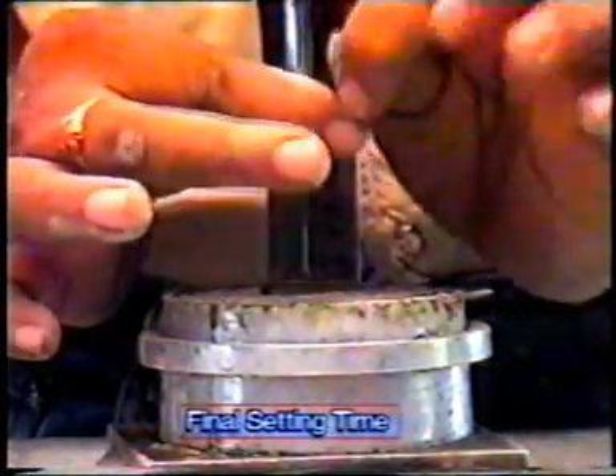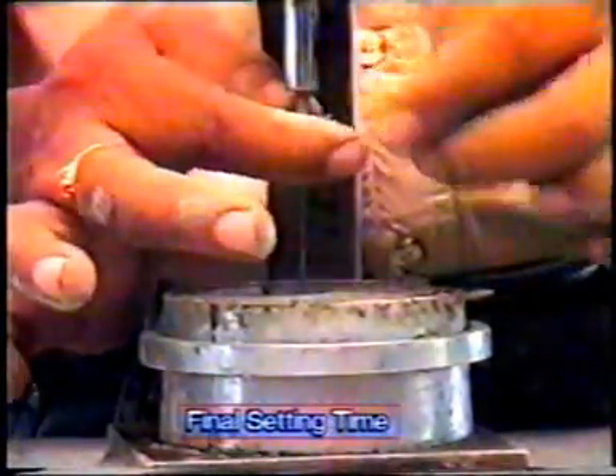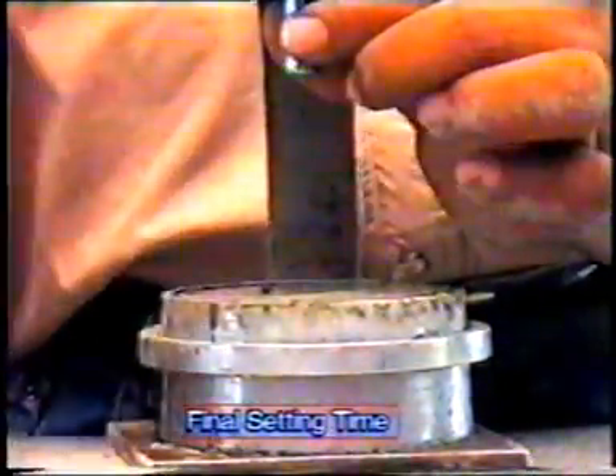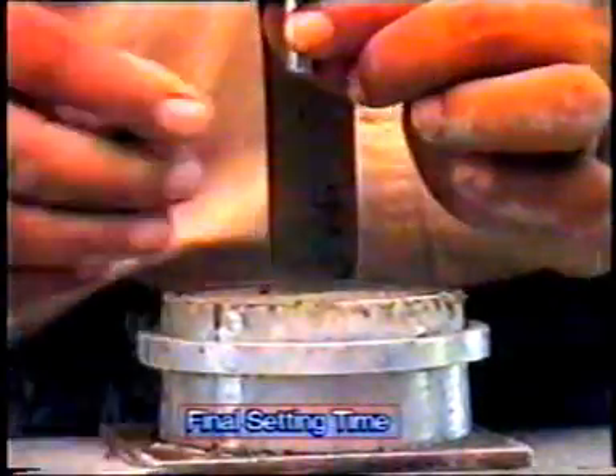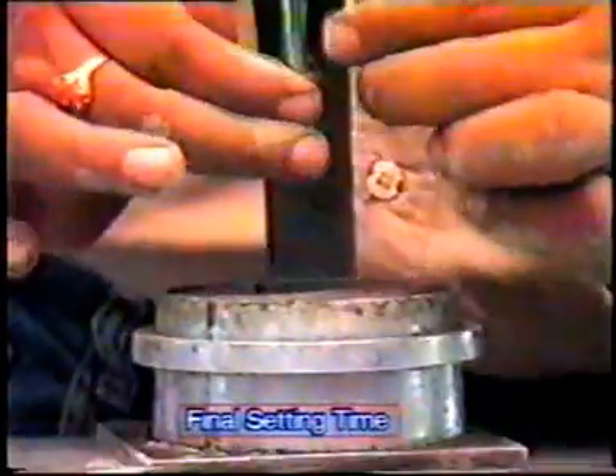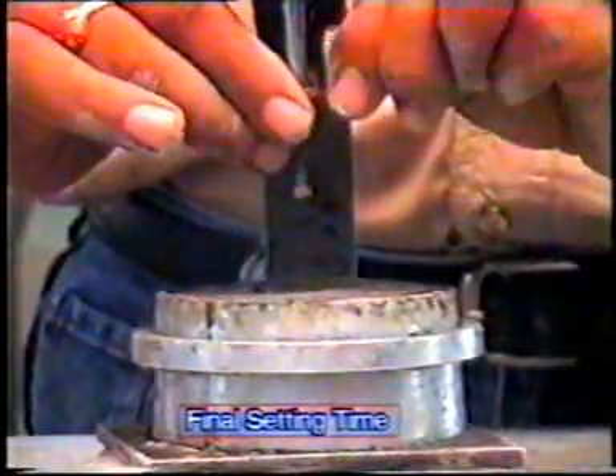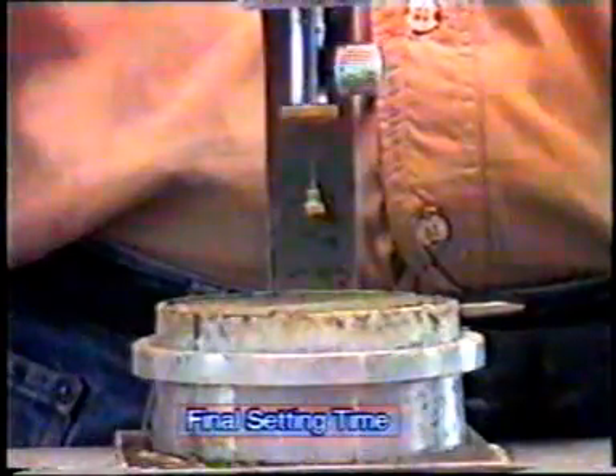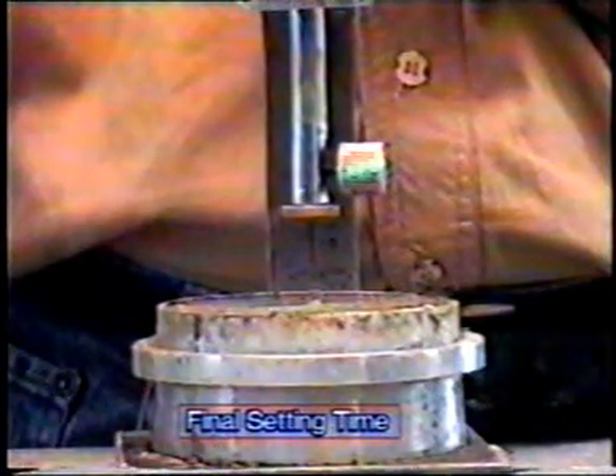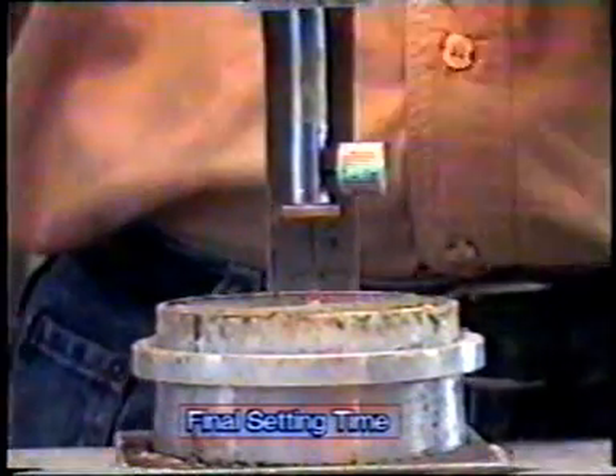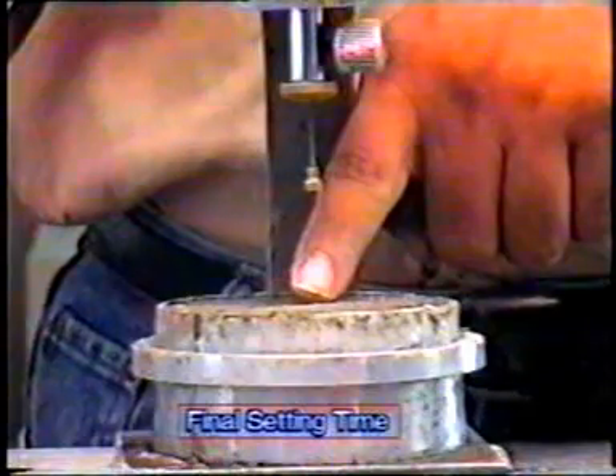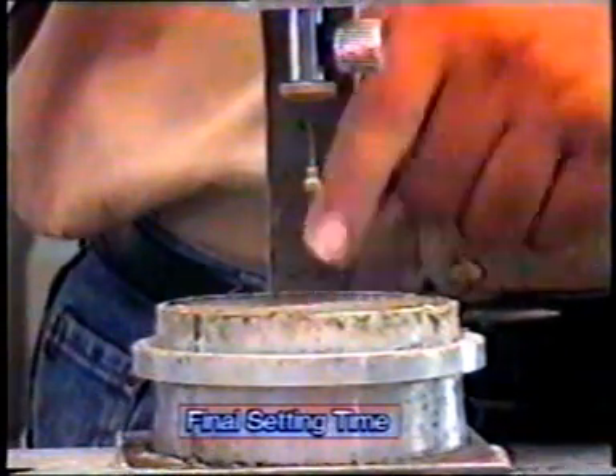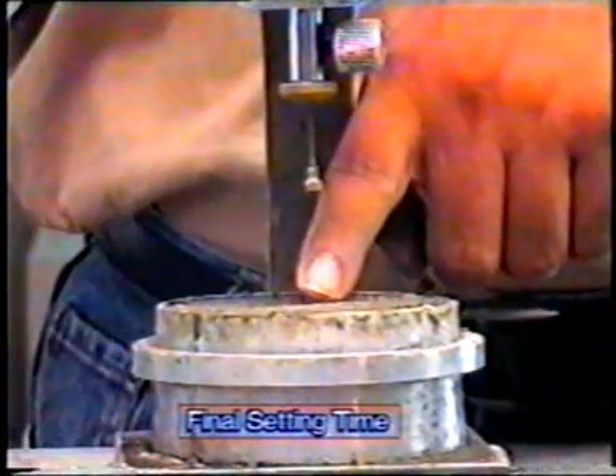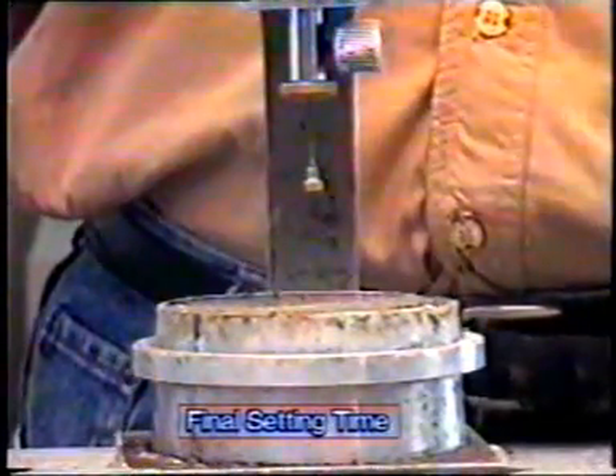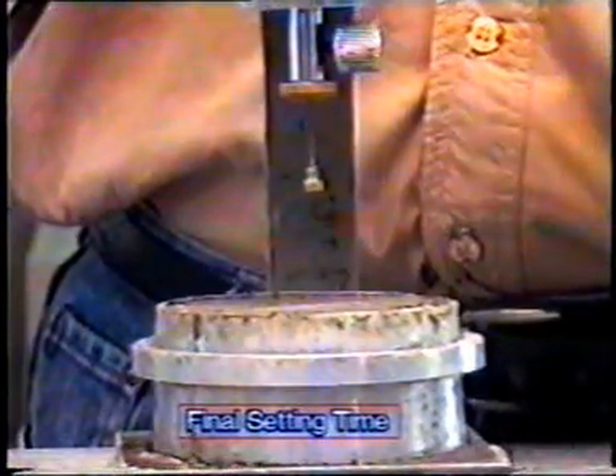Now for the final setting time, replace the needle of Vicat's apparatus with a needle with annular ring. The needle is gently applied on the surface of the test block. Now you see not only the needle but also the outer ring has made an impression on the sample. This means that the final setting time of cement has not yet been reached.